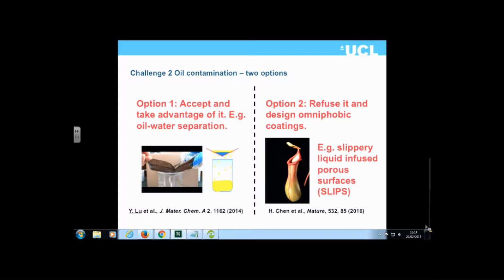This is where the slippery, liquid-infused, porous surfaces come from. The slip surfaces are actually superhydrophobic surfaces that have been treated with a lubricant. If you put a very thin lubricant layer onto your superhydrophobic surface, you can make that surface resistant to virtually any form of staining.